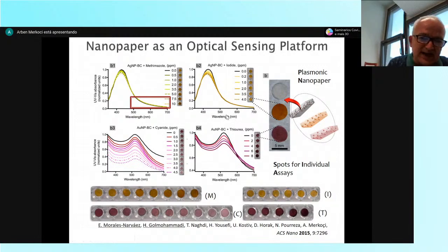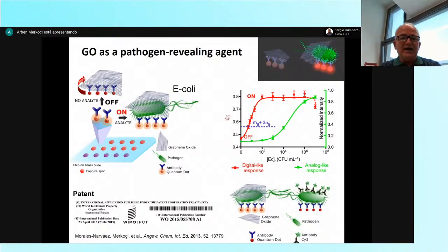Of course, this is not selective because if we have these in presence of each other, they will interfere, of course, but we can make it selective. And in fact, I'll show you an example where we played with these and then using, in this case, in addition to quantum dots, we use graphene oxide as a quencher of the fluorescence. And we built a very simple system that is based on the quenching of the fluorescence of quantum dots when these are in contact with graphene oxide.